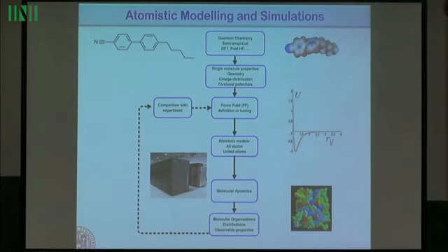And these atoms could be of the order of 100,000 atoms, 100,000 little spheres that have to be evolved in time. So this is simple in principle, but for molecules of this complexity, for a set of temperatures necessary to locate the phase transition, it can easily take of the order of 100 years of one processor. But of course now you use parallel computing with maybe hundreds or thousands of processors, and if you manage to distribute the work in this parallel computing sense, then it will take a more manageable time, but still many weeks or months.